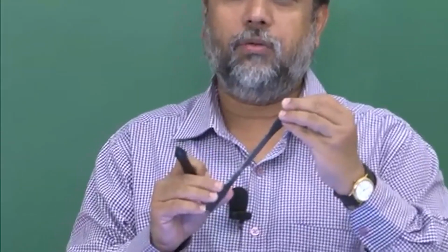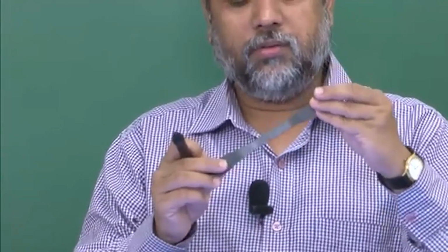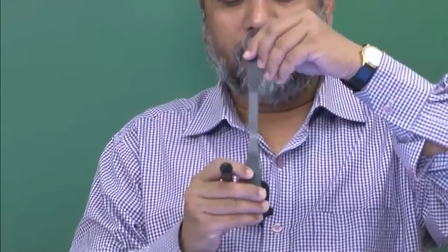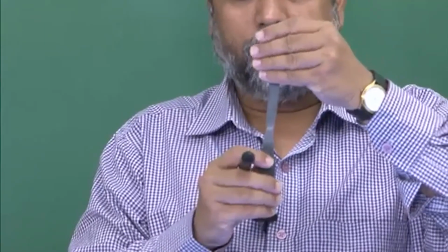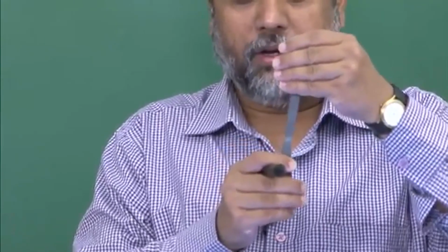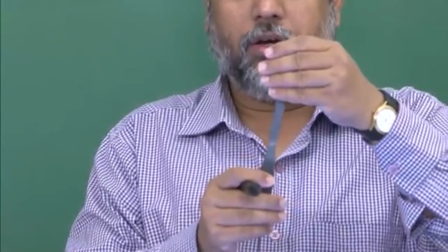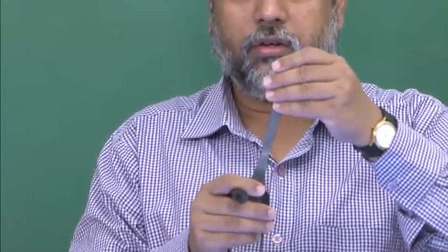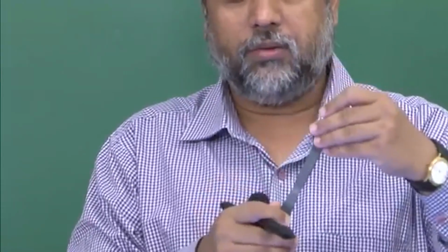So, you have to make this dog bone shape, and this kind of dog bone shape is very difficult to make, for the necking etc., for the ceramic sample. So, sample preparation is the first important problem. The second problem is that in tensile testing, we put these areas for gripping, but this gripping for ceramic material is enormously difficult.